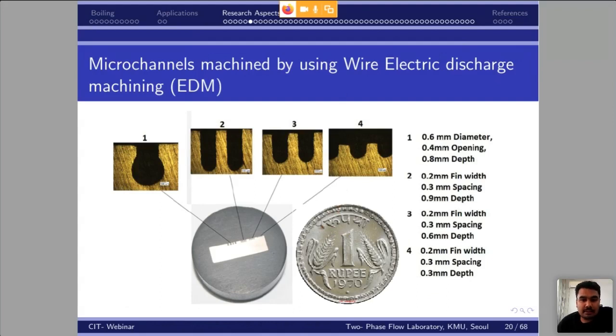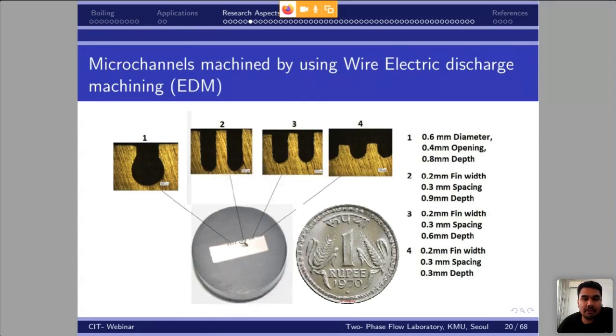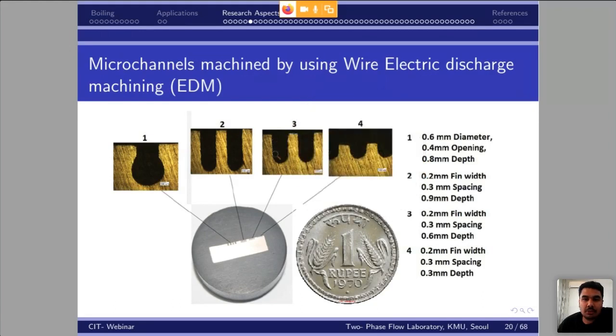Regarding the channel size, you can see this is a comparison for different sizes of channels. This is the sample we have taken to mount our channels. You can see different channels have been machined using an EDM machine. And for size comparison, we have given a 1 rupee coin also here. You can see here the different size channels. This is actually a 0.6 mm diameter channel. You can see this is U-shaped because of the EDM wire diameter actually.